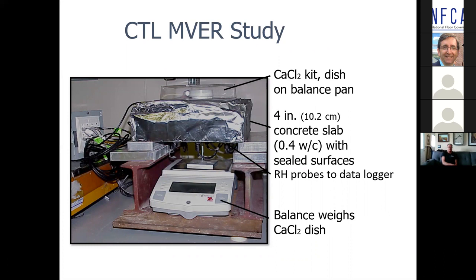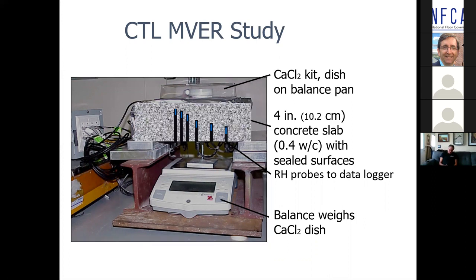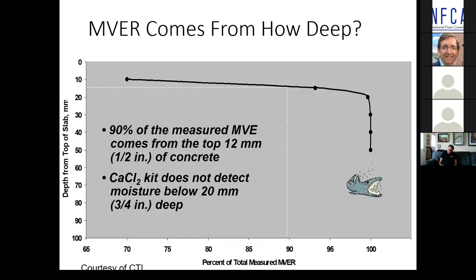And this is a study that my friend Howard Kanare and my colleague Scott Tarr performed years ago when they both were at Construction Technology Laboratories in Illinois, where they took a 4-inch concrete slab and had humidity sensors embedded into that slab. What they were trying to do was determine where the moisture was coming from, the moisture that you could see on top of the slab in a dish of calcium chloride pearls underneath a plastic dome. Where was the moisture that the pearls were absorbing, either by emission or hygroscopic action, coming from? And what they found was that it was only the top half to 3/4 of an inch. Nothing changed beyond 3/4 of an inch into that concrete.